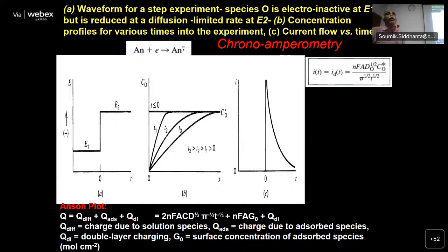Interestingly, instead of current, if I monitor the charge, that means quantity of current flowing, instead of I, I measure the integral of I dt, the total charge. If I monitor the charge with respect to time, I have a lot of advantages here. Cottrell equation tells you current variation with respect to time: I is proportional to t to the power minus half. If I plot Q, the charge, versus time, a very interesting plot, there is a plot called Anson plot. Simple Cottrell plot is current versus time, but Anson plot is quantity of current versus time.